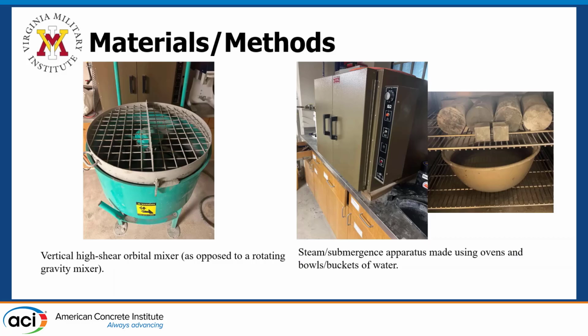So some of the materials and methods we used. Granted, this is a concrete mix that used a low amount of water and was incredibly heavy due to the use of steel fibers. So we had to use a vertical high shear orbital mixer, which presented its own complications. A lot of the time we had to reverse it in order to cut through the concrete because it would end up pushing it around.